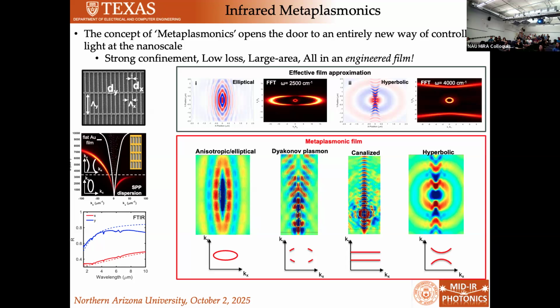Now, what that means is that you actually have an anisotropic metal, right? Metal, of course, is isotropic. You deposit a metal, there's no way to tell X and Y. But here we can engineer the optical behavior of our metal in the X and Y direction. And what that means is that we can engineer these propagating modes. If we put a dipole above this surface and we look at the field, we can measure the field generated by a dipole. And you can see that this is what we call an elliptical dispersion, right? The waves have different k vectors in the different directions that are generated by this dipole.